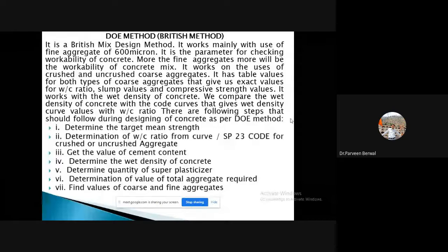It works with aggregate of 600 micron. There are different parameters that we use in the DOE method. First, we determine the target mean strength, determine the water cement ratio from the curve of the SP23 code, the cement content, then determine the wet density of the concrete and the quantity of the superplasticizer that we use. Then determine the value of the aggregate, whether it is fine or coarse.